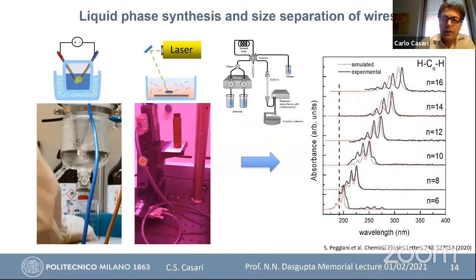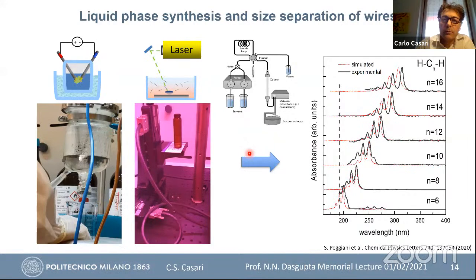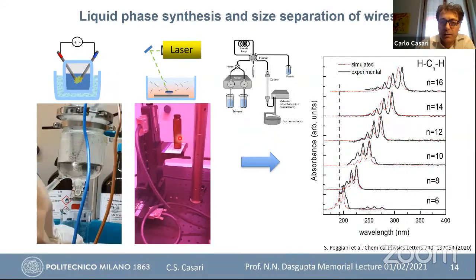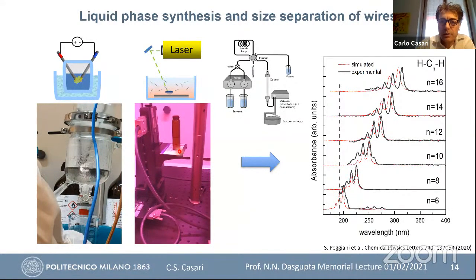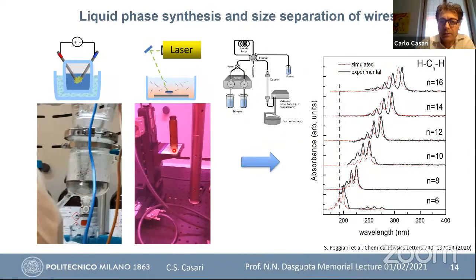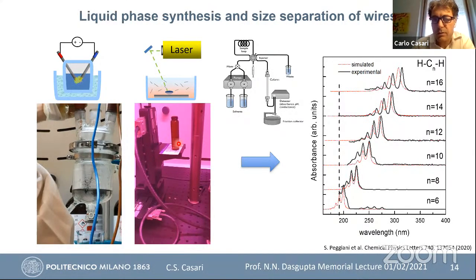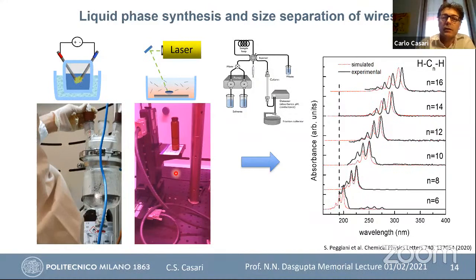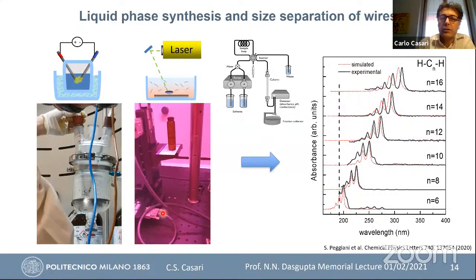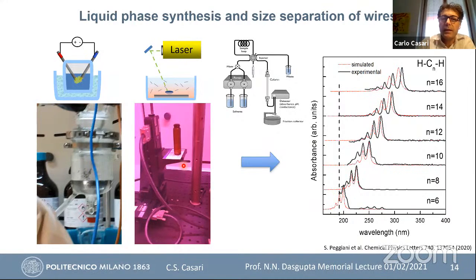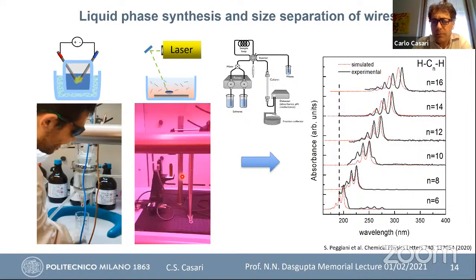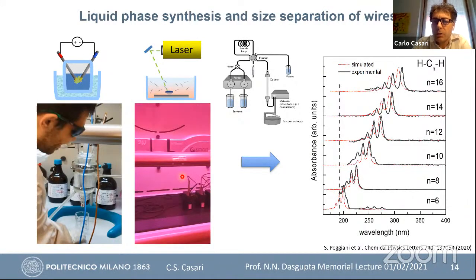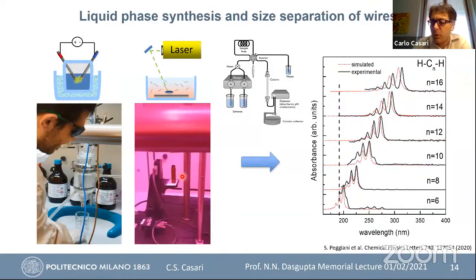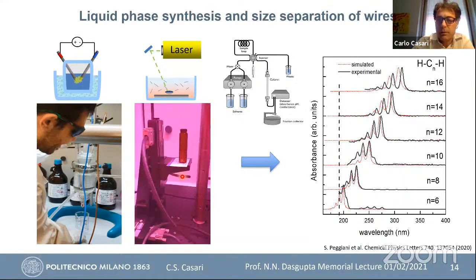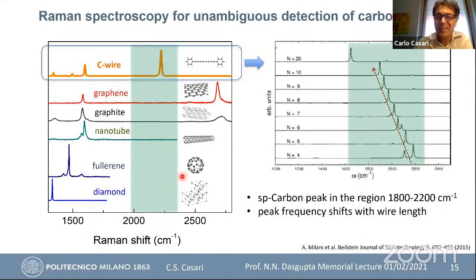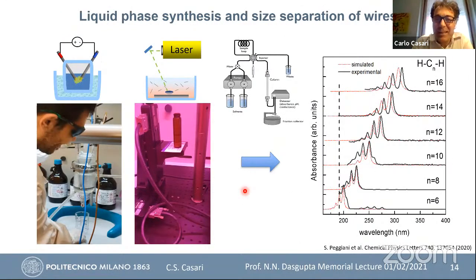In the same way we do pulsed laser ablation. You see here the laser shot that is focused on a graphite target in the presence of a solvent. In this way, again, by tuning the laser parameters and the type of solvent, you can tune the type of carbon atomic wires that you form. Okay, sorry, I stopped. The noise is not very nice.